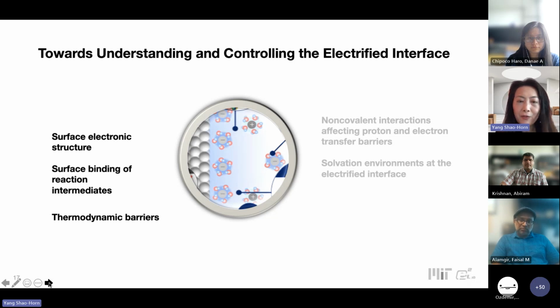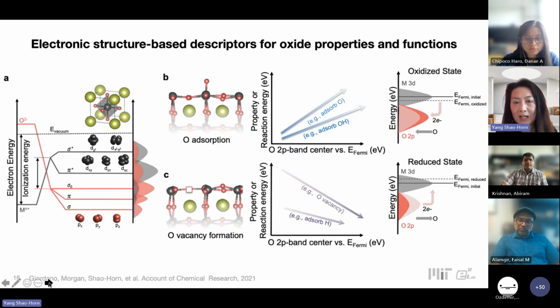So we're going to begin with the first: how do we tune the covalent interactions? The basic idea is that we can control the adsorption and desorption of oxidizing species or reducing species by essentially moving, let's say, an electron from the D states to the oxygen P states upon adsorption of oxidizing species. And the driving force for this adsorption would decrease if we go to a later transition metal, with a higher oxidation state.